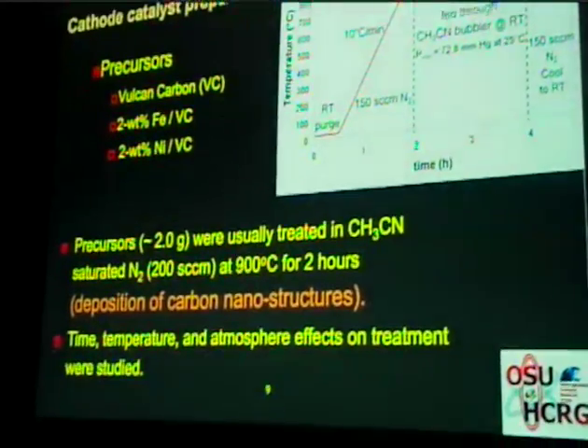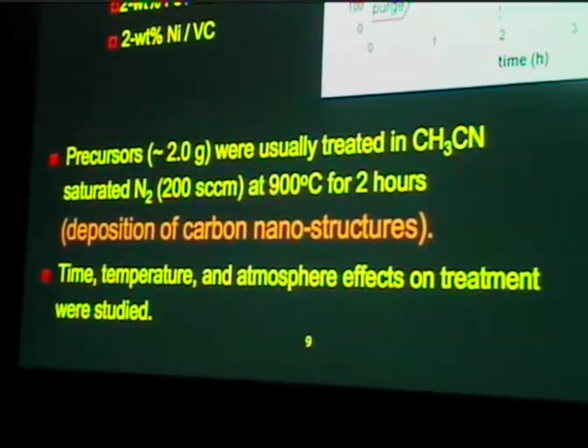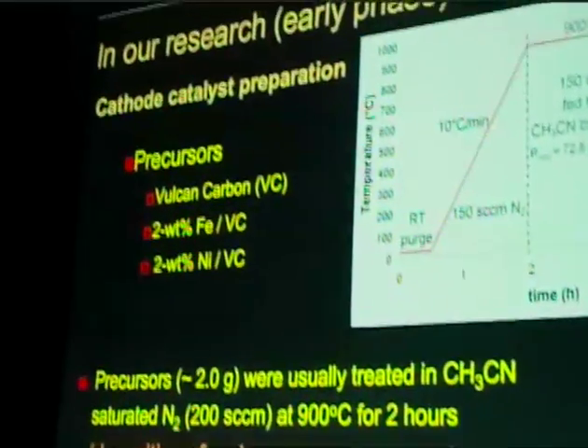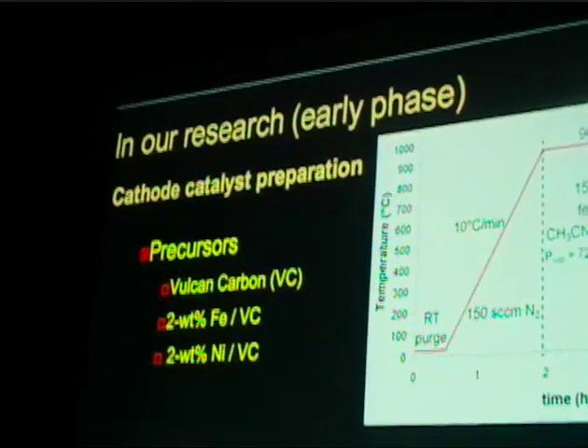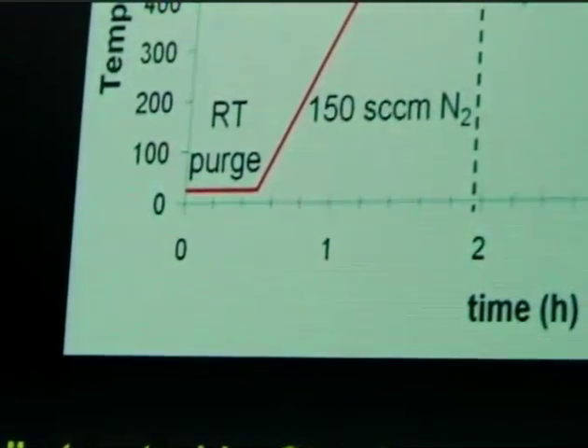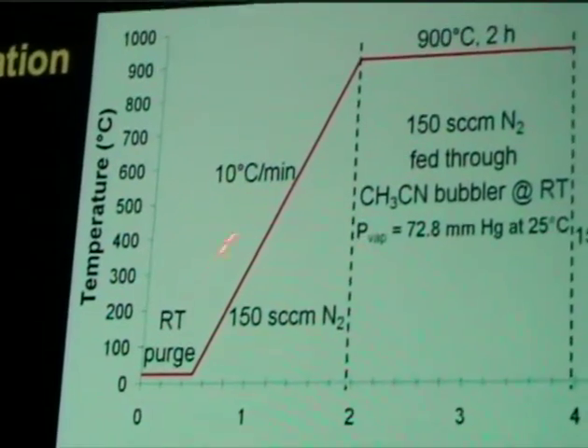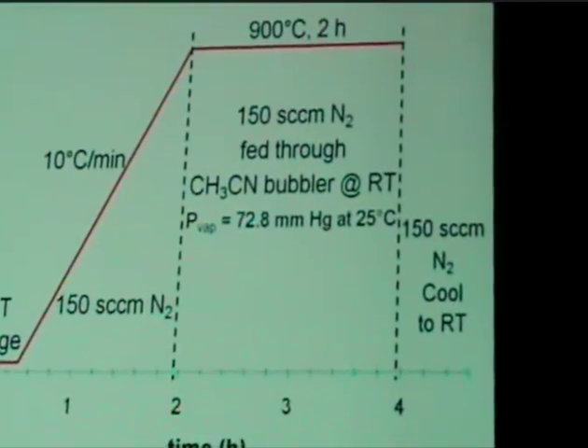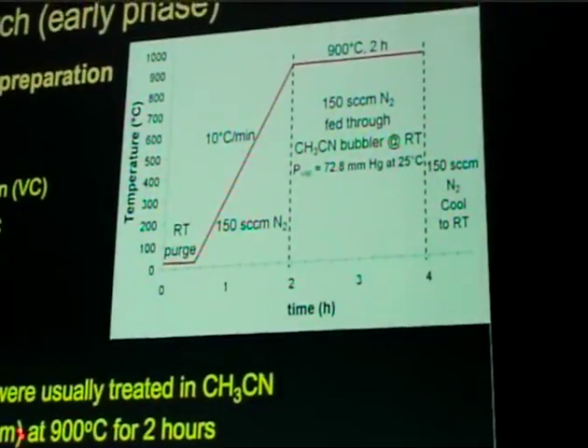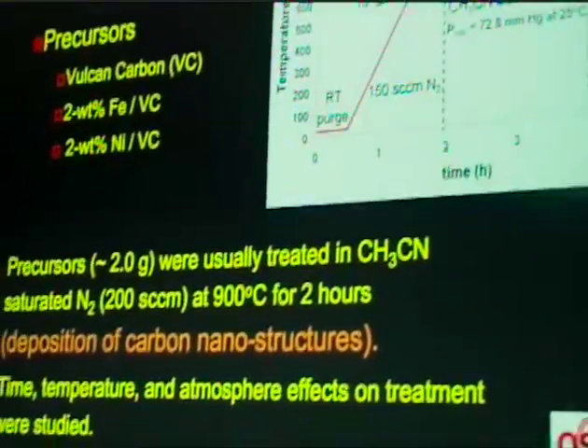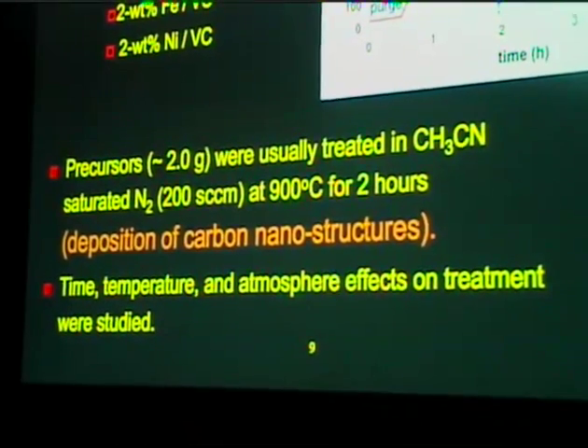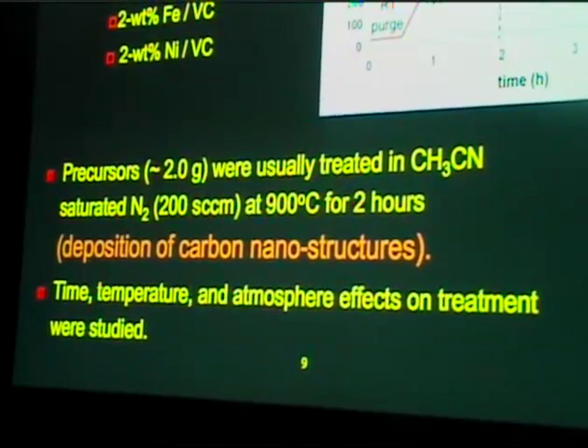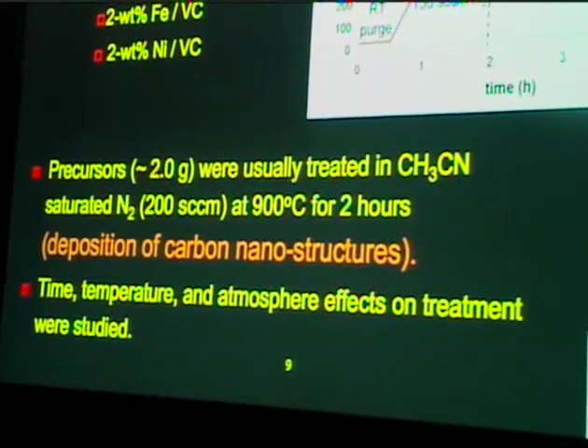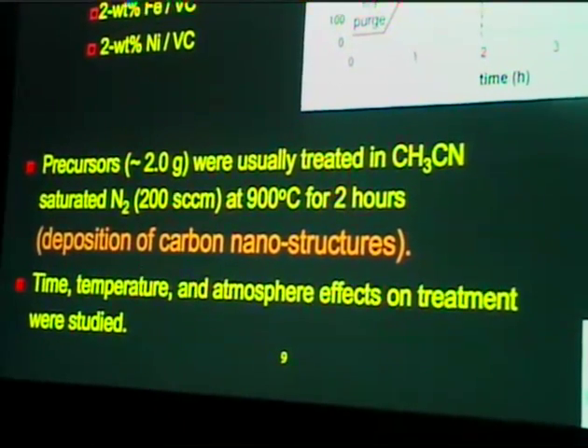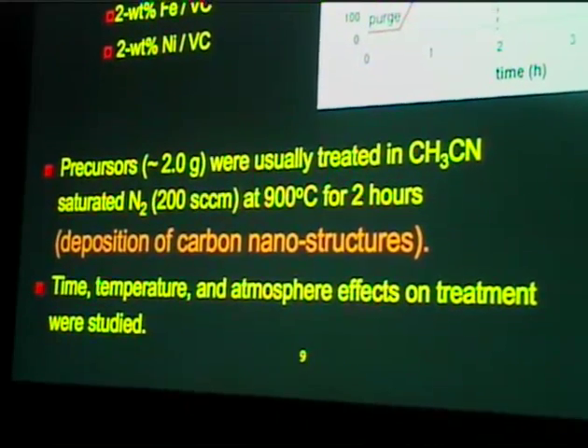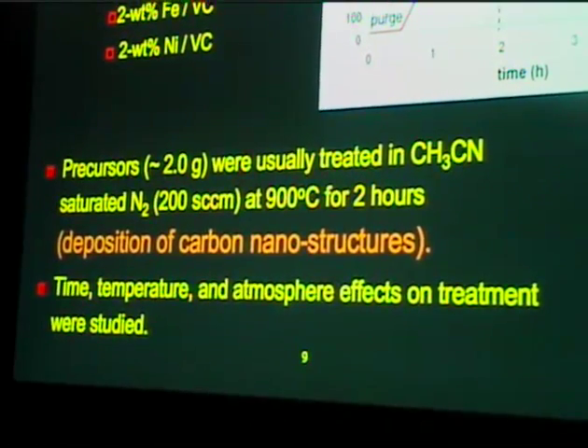So in our early research, we started out using Vulcan carbon as a support material, which is also the support used for platinum, doping it with some metals, and then going through an acetonitrile decomposition or a pyrolysis treatment. In this case, we are saturating nitrogen with acetonitrile and then exposing the Vulcan carbon to this environment at 900 degrees centigrade. This is really a deposition of the carbon nanostructures. And we looked at the effect of time, temperature, and atmosphere on the treatment.